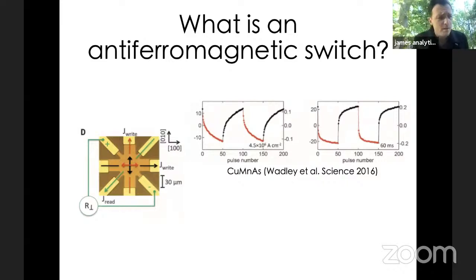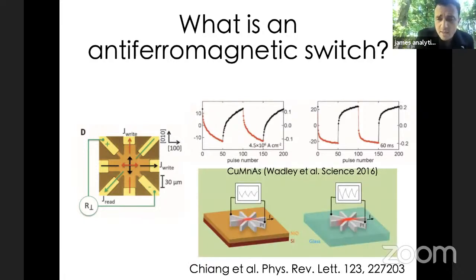Now, there was a bit of a different take on not these particular systems, but interfacial systems, where people suggested that there might be heating, that could also be a source of this kind of switching. So there was a paper by Chiang and others that appeared at the end of 2019, where they did a similar experiment, but actually on a dummy substrate. And what they showed was that just through the heating caused by the electrical pulses, you can actually get a very similar kind of sawtooth type structure. So the point of that paper really was that multiple effects might be happening when you're doing these kinds of experiments.